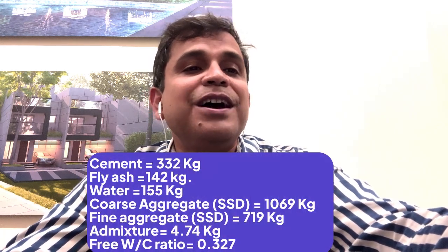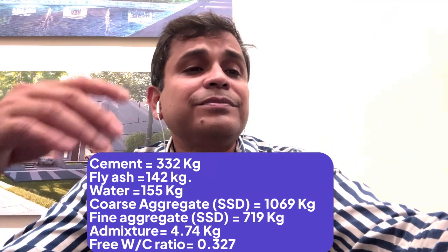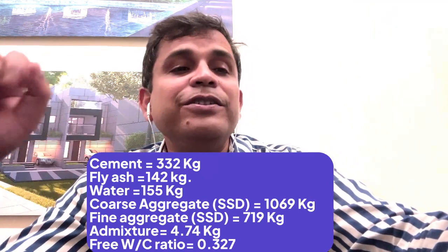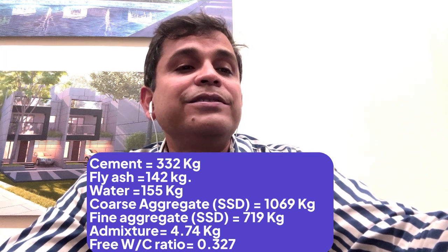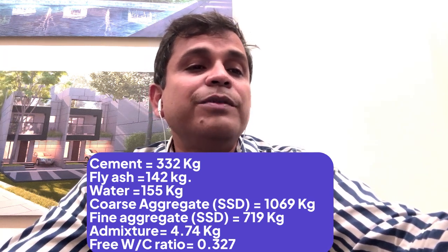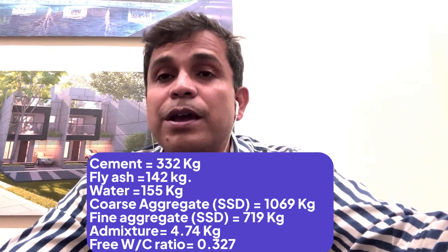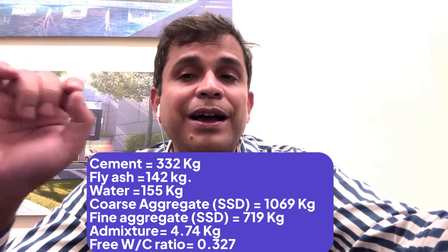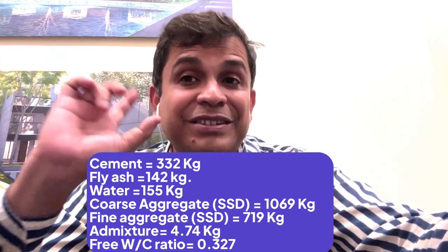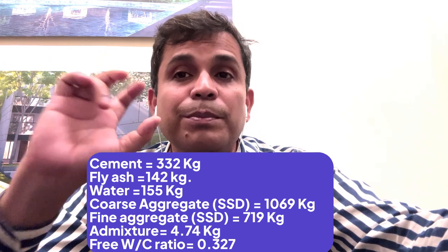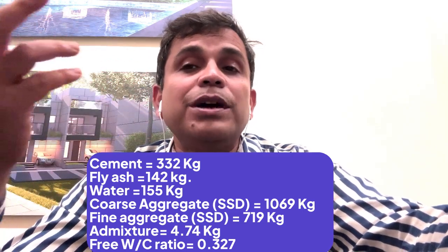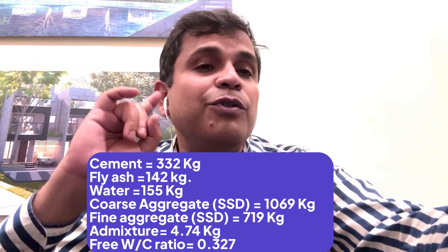So, here I have an example. In this example, I have cement equal to 332 kgs, fly ash 142 kgs, water 155 kgs, coarse aggregate in SSD condition 1069 kgs, fine aggregate 719 kgs, admixture 4.74, and water cement ratio 0.327. Now, when calculating the moisture percentage in the mix, I found 4% for the fine aggregate and 1.5% for the coarse aggregate.